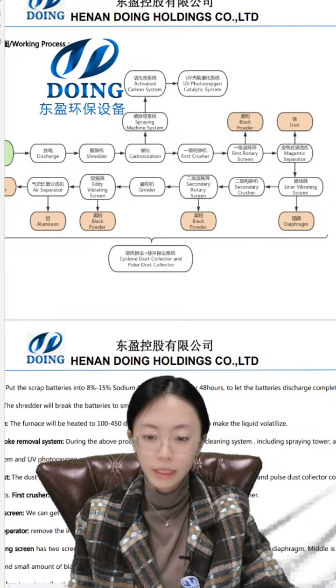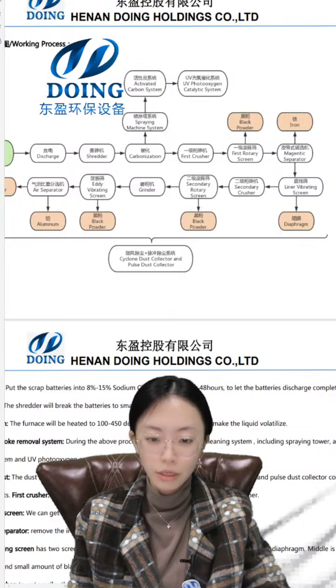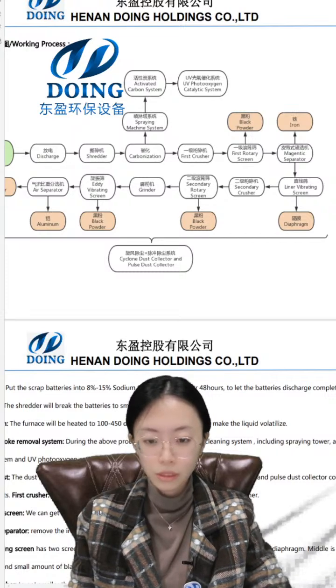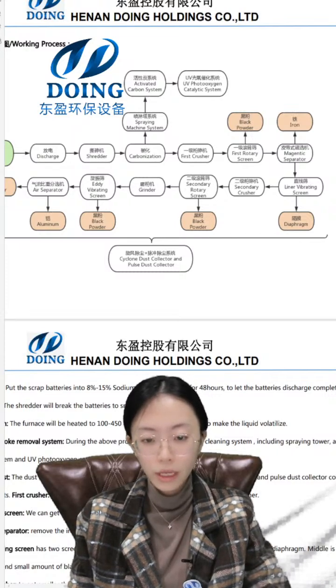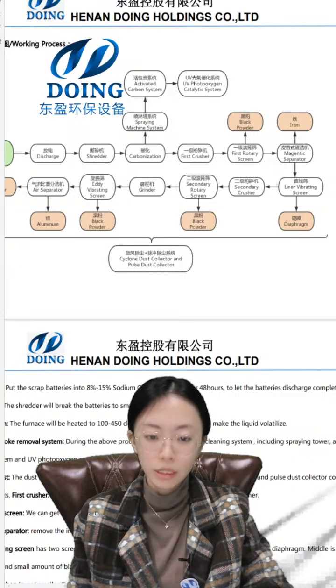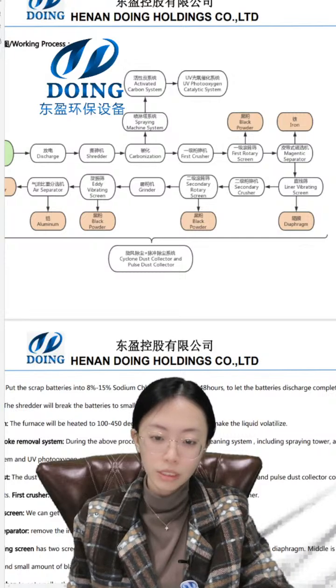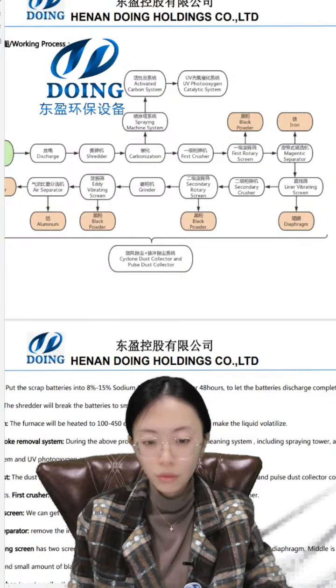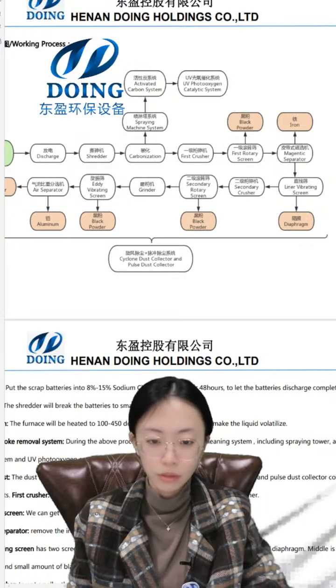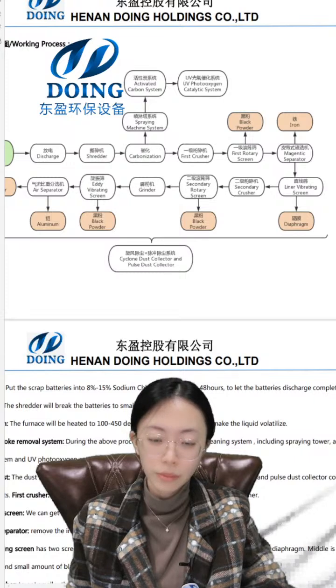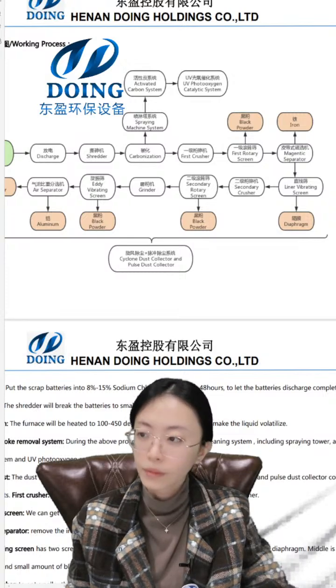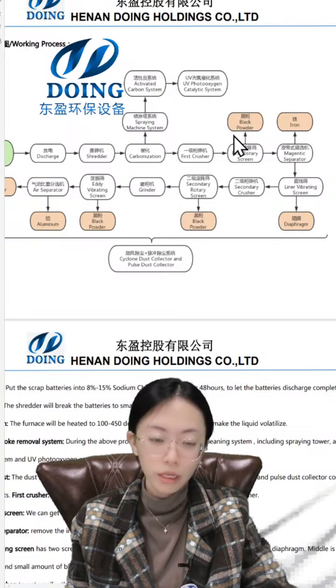And then we come to the first rotary screen. It is linked to the crushing machine, and the material will use the sealed vane transfer system to send the material into the rotary screen. It has a 120 mesh screen surface rolling the materials, so the qualified material, the black powder, will discharge through the screen holes. And the black powder in this step has a recovery rate of, sorry, 60 to 70%. This is the first black powder we can recycle.